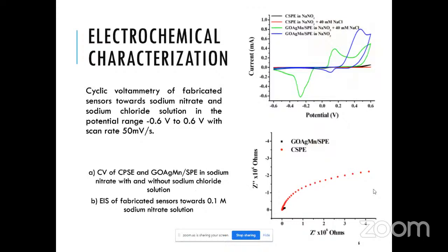In electrochemical characterization, the fabricated sensor was tested in sodium nitrate medium with and without the presence of chloride ion. It can be seen that for the bare electrode, that is without the catalyst, there is not much current response in comparison with that of the electrode coated with our material. The impedance spectroscopy also agrees with this.